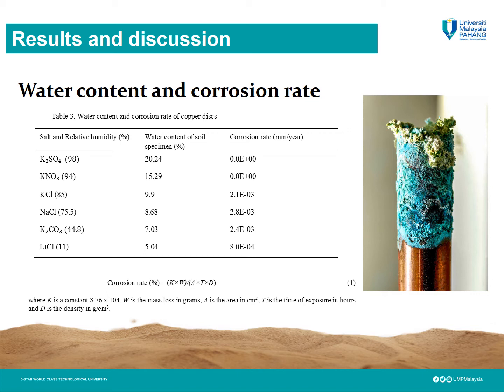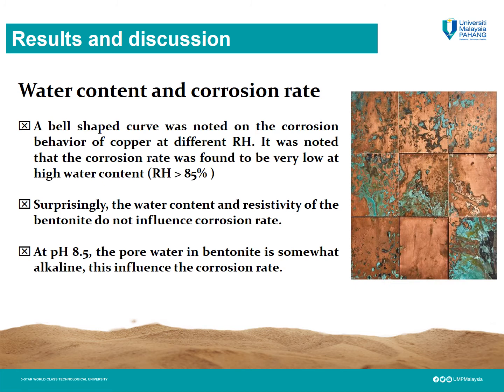A bell-shaped curve was plotted, and it was noted that a relative humidity of 75.5 to 85% actually generates corrosion to the copper electrodes. At a very low relative humidity and at very low water content of bentonite, a very low corrosion rate was found. So a bell-shaped curve was noted on the corrosion behavior of copper at different relative humidities. It was noted that the corrosion rate was found to be very low at high water content, higher than 85%.